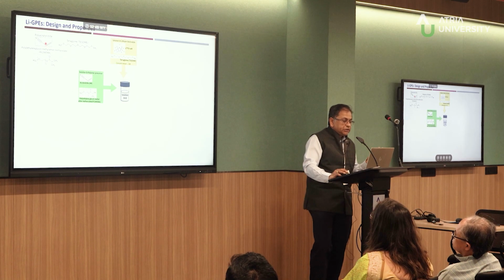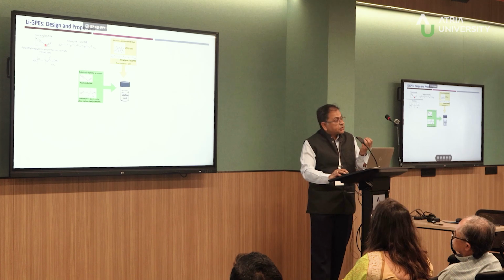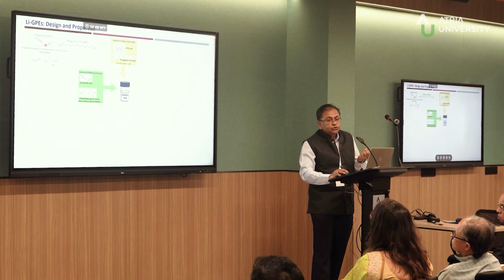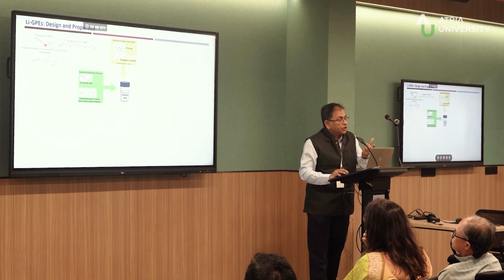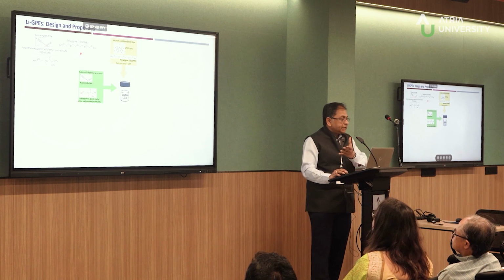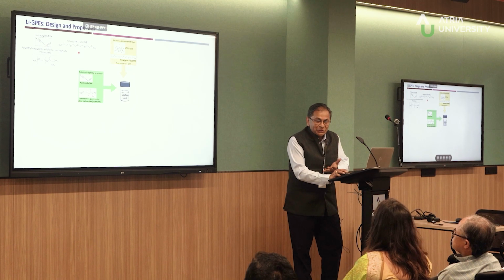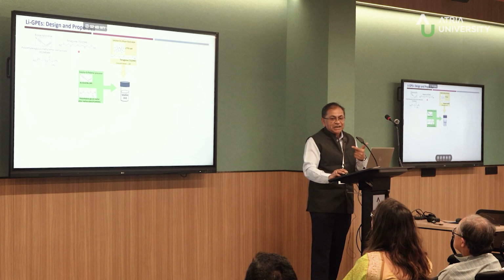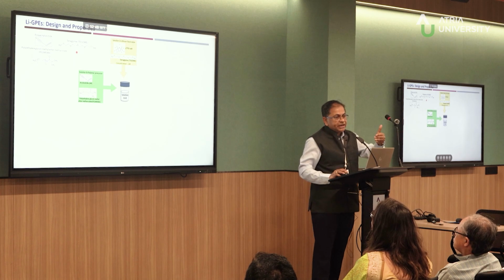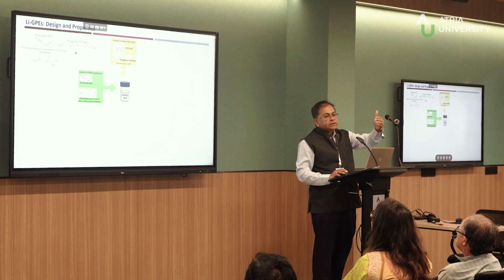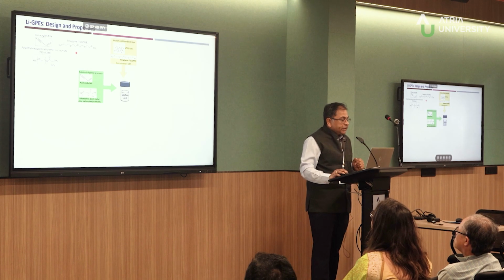So you have a component, which can very easily solvate an ion, but then too strong a solvation will not give you a good conductivity. So what you do is, I think, you use succinonitrile. So we use similar molecules to plasticize it. So you actually render dynamics. You actually move the lithium or sodium much faster. Okay, so